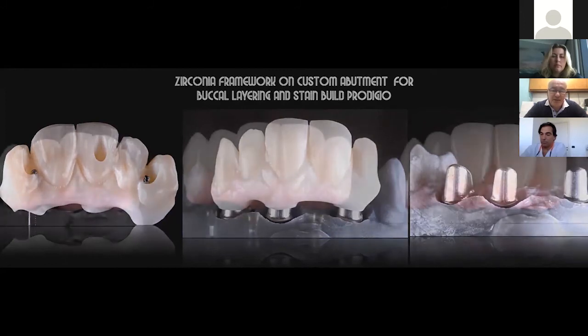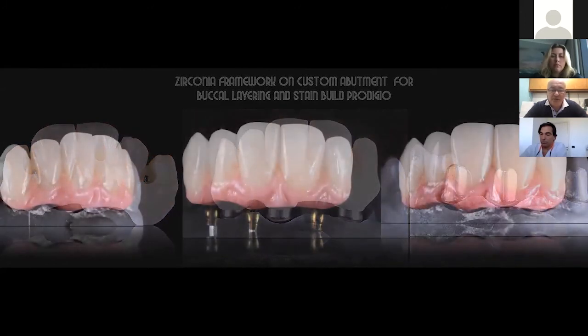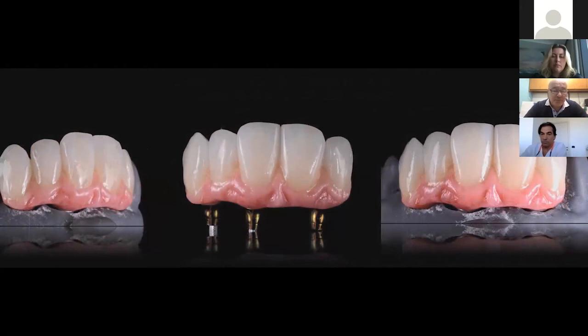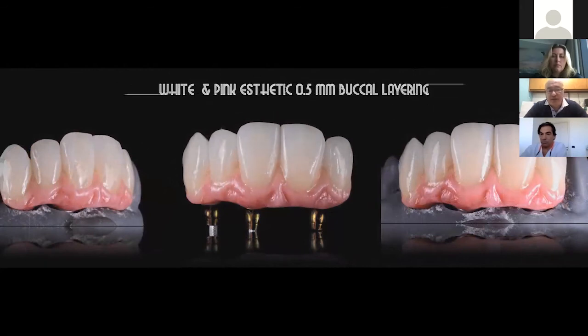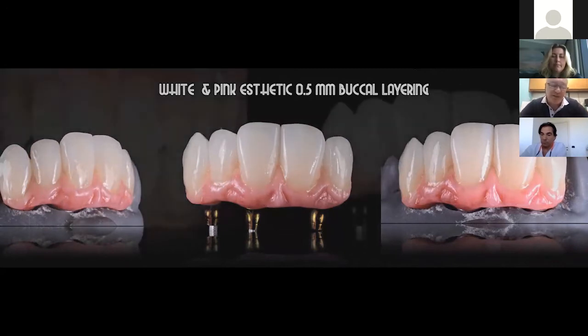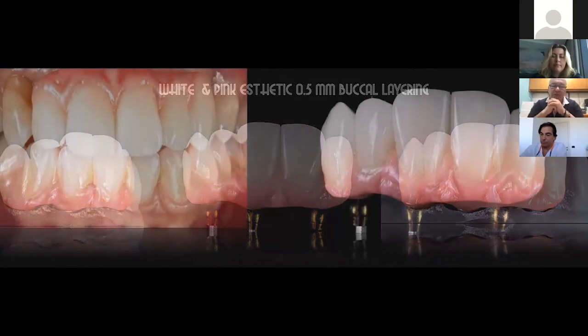In this situation, we didn't do any infiltration. We didn't use any stain at the pre-sintering stage. We just decided to do a minimum layering on the buccal with the porcelain, and on top of this, we finalize both the white and the pink area with Prodigio stain buildup. It's a very minimum layering. We're talking about 0.5 millimeter.